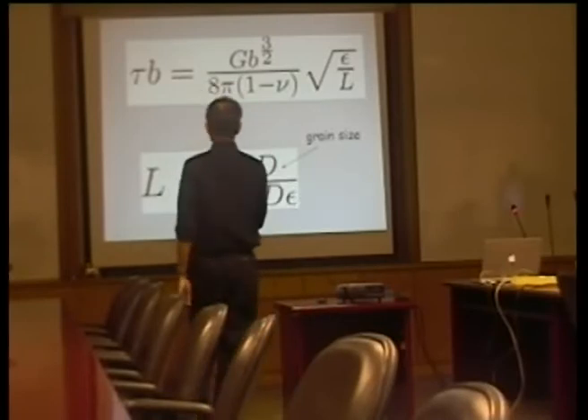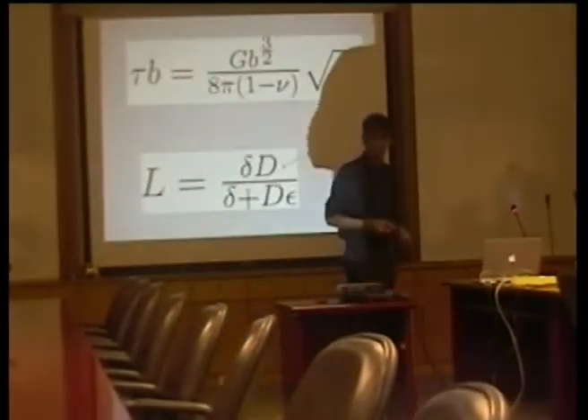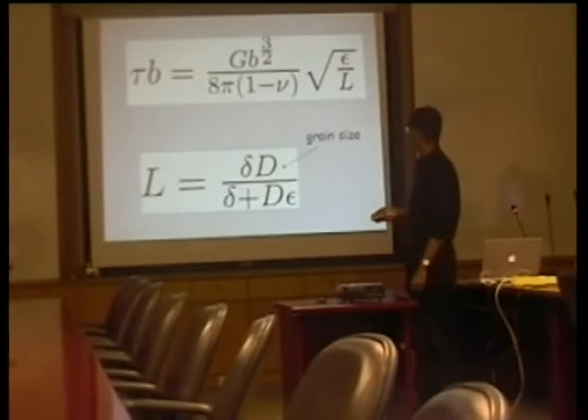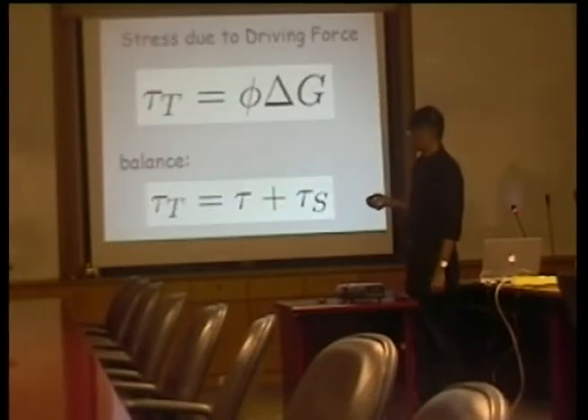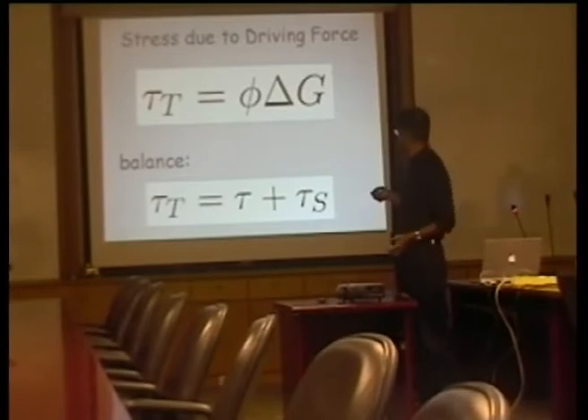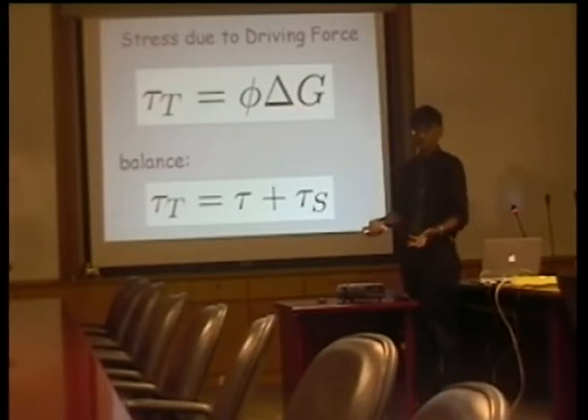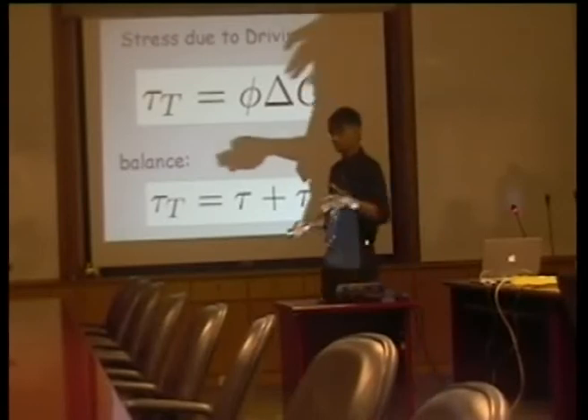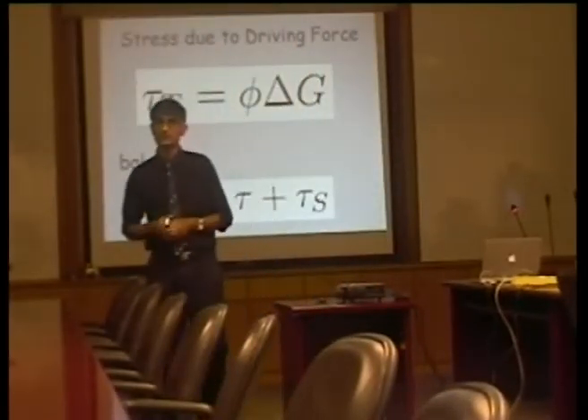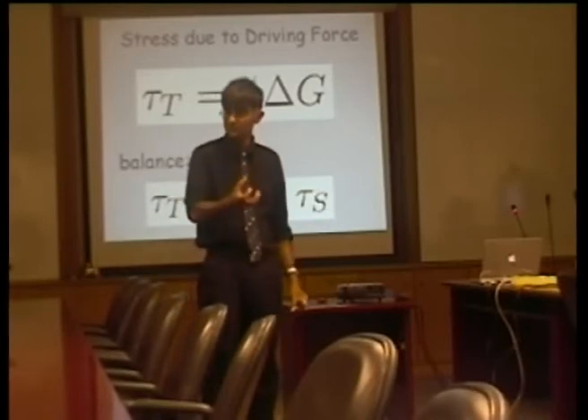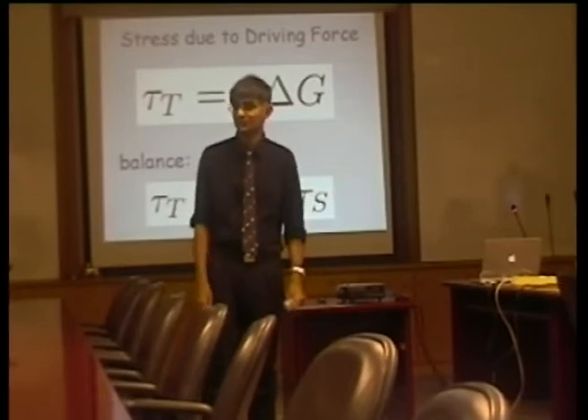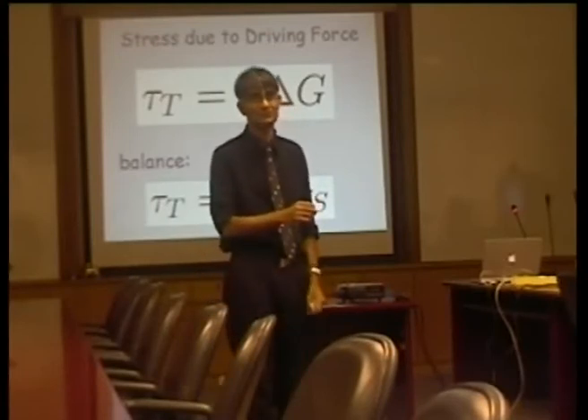So this is the stress required to push against dislocations, which we have introduced by deforming the wire. And this is the stress that pushes the interface because the austenite wants to transform. This is the free energy change when austenite transforms to martensite. So we have two stresses. One is the stress required to overcome dislocations, and one is the stress which is pushing the martensite-austenite interface because there's a free energy reduction when austenite transforms to martensite. If we balance those two, we can predict the strain at which we should get mechanical stabilization. Is everybody happy with that concept?